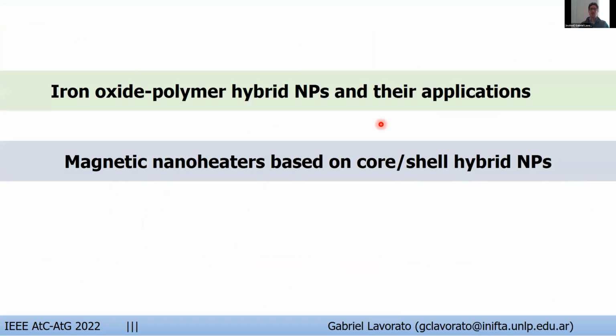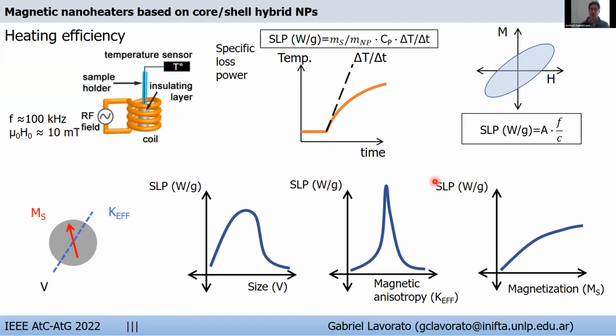So let me now move to show you some results on magnetic nanoheaters based on core shell inorganic nanoparticles. The heating power of a magnetic colloid under an AC field can be recorded in a calorimetric setup, as shown here, where the specific loss power can be estimated by recording the initial slope in a temperature time curve, as shown here. So to achieve large heating powers, we need a large saturation magnetization and a fine-tuning of the anisotropy and size of our material.